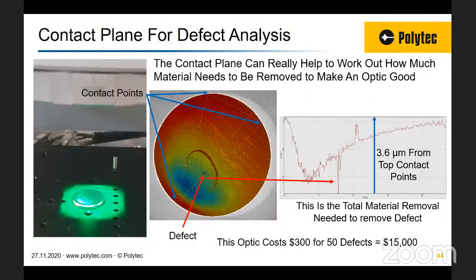You can then take that step further. Here you have a simple optic. You can see a pen mark there. We actually measured the pen mark on the optic. It has a defect, and by applying the contact plane, you can apply it to any surface situation type. You can now see the total depth of this defect from its complete surround.